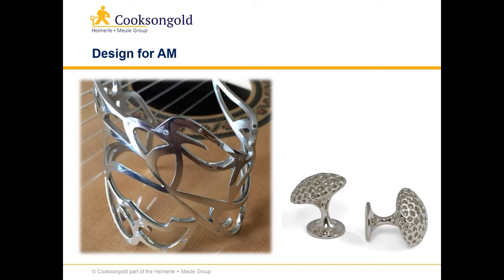This particular piece, the bangle on the left-hand side, is once again completely hollow, and we reduced the weight by about 50% once again in a platinum product. The stones were set afterwards, they weren't set during the build process.